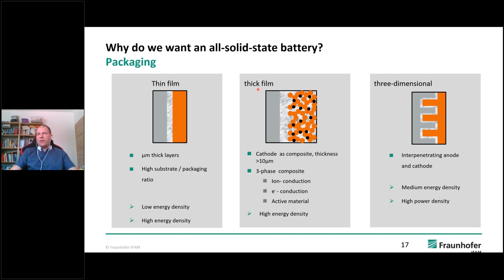On the other hand, we have the thick film, which is the direct translation of the classical lithium ion battery. So we have a composite cathode, a thick composite cathode, thicker than 10 micrometers, ideally even 100 micrometers. The challenge here is that we have a three-phase composite. We have a lithium ion conduction material, which has to be the solid electrolyte. We need some electric conduction, which is mostly done with carbon. These are the black dots, and some active material. In a perfect world, we would just use the orange one, because we get the best energy densities, calculated from the theoretical value, when just using the active material. So if we can build these cells, we get the high energy density cells that we actually want to have.